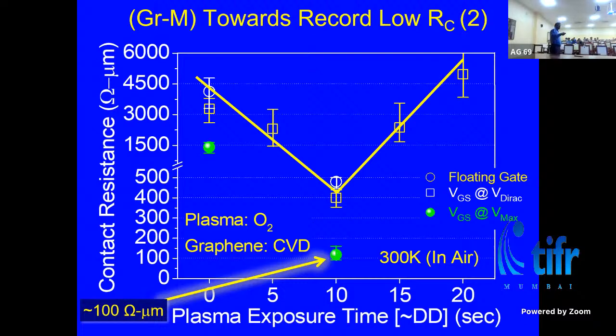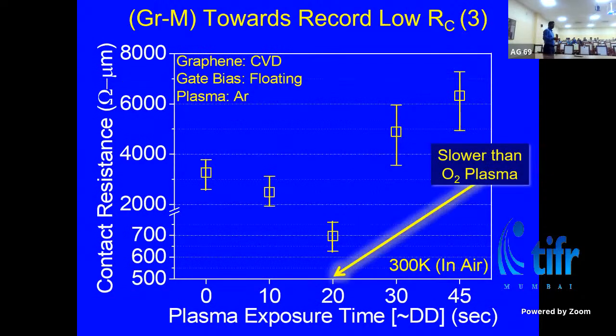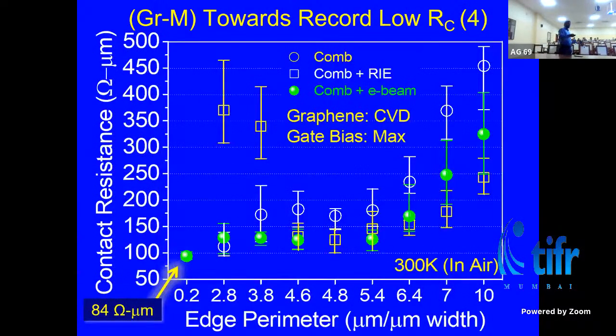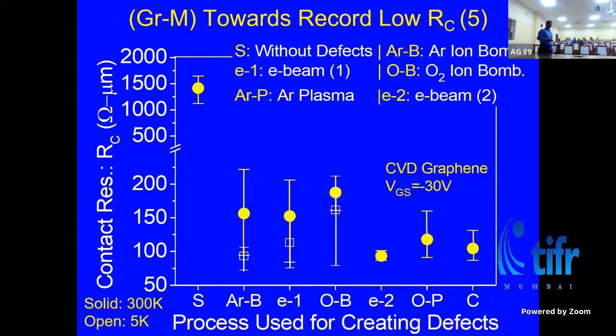But as it shows, there is a big difference in the contact resistance as a function of gate bias when the contacts are not engineered. But when you have engineered contacts, the difference reduces. And if you also see the variability in the contact resistance from one device to the other, with around 40 devices per data point if I remember correctly, the variability also comes down when you have engineered contacts. So in this case, the lowest contact resistance also has the least variability, and that's why we chose this for our further transistor-level developments and investigations.